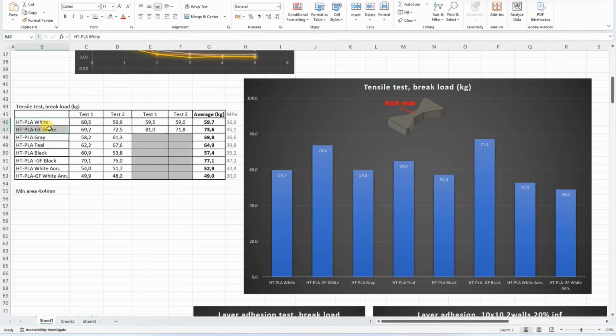So from these test objects I have 4, because 2 are printed in the color comparison group and 2 are printed in the main group, and we can see that a regular HT-PLA has very similar strength in all 4 cases. Here we can see some small peak but nothing significant, and we can see that the glass fiber version is stronger, and annealing doesn't really help, actually it reduces the tensile strength.